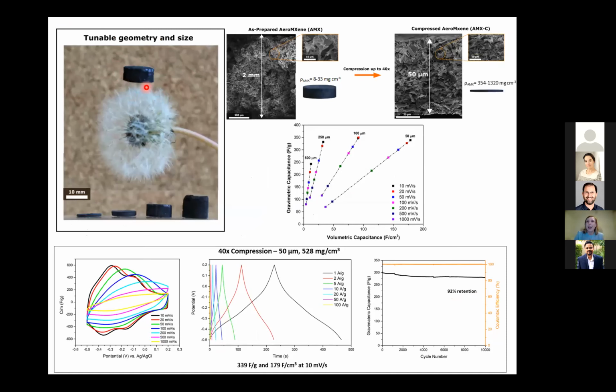This is how light they are, and the good thing is that you can really build any sort of structure that you want, give them the shape that you want. And because we're using them as supercaps, we also wanted to increase the performance that we could obtain. So we added some compression steps in order to get more material down. So for a compression of about 40 times from here to here, we managed to control the density of the material, and indeed we managed to get a very, very good electrochemical performance. So this is a very, very nice achievement, and also a very, very nice and stable performance.